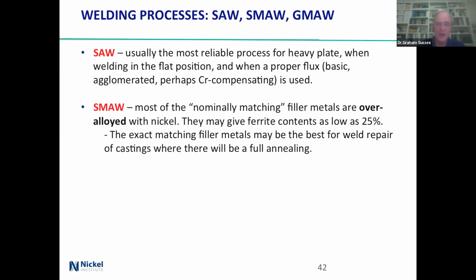Shielded metal arc, nominally matching filler metals. Unfortunately, they're usually over-alloyed with nickel, which is all very well, but as it cools down, you're going to get lots and lots of ferrite taken away, as low as 25%. And that's getting to the bottom end of what you can actually get and still call it a duplex. So you may be better off just accepting the recommended matching filler metals. Certainly if you're doing weld repair on castings, you would be full annealing, and so you'd have to match it up fairly nicely.